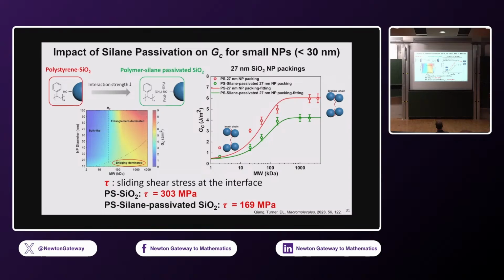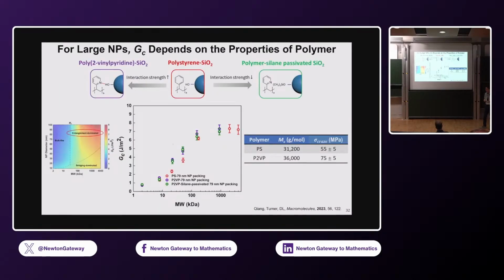The red is when you have silica and polystyrene. Green is when you have silica with passivated silica. I'm sorry, polystyrene with passivated silica. And you see that there is a decrease in the toughness of these materials. And that's understandable. For small particles, like I said, it's the bridging that dominates the toughening mechanism. So when you weaken that interface, your toughness is not as high. Now, for larger particles, the story changes.